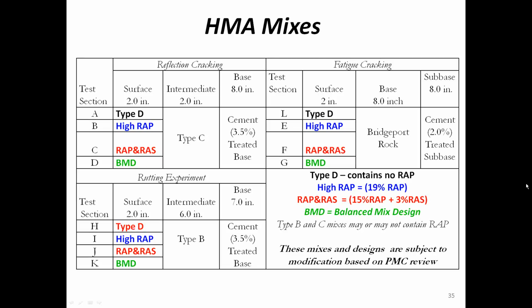Stefan, the only other comment that I would make is regarding the load level in these mixes and your laboratory testing plan, as you know, because I've discussed it with you in the past. We continue to find that the performance of higher recycled content mixes is highly dependent on the strain rate in terms of cracking performance. So it was really encouraging to see that you haven't set your test plan up to superload these sections, because under superloading with much higher, unrealistically high strain rates, I'm sure you would find high crack susceptibility in the treatment test sections.